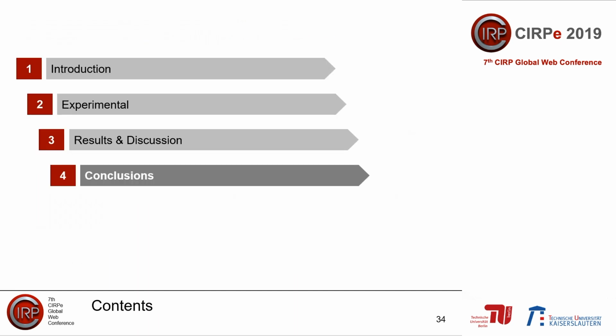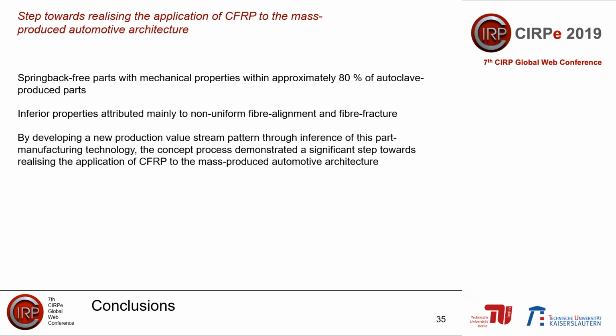So on to conclusions. We managed to produce spring-back free parts with mechanical properties within approximately 80% of autoclave produced parts. The inferior properties from the concept process are mainly attributed to non-uniform fibre alignment and fibre fracture during forming. But importantly, we believe that from our process we have made a significant step towards realizing the application of CFRP to the mass-produced automotive architecture.